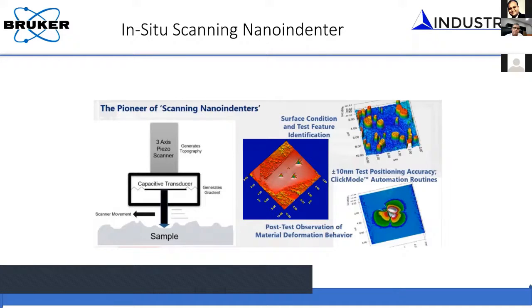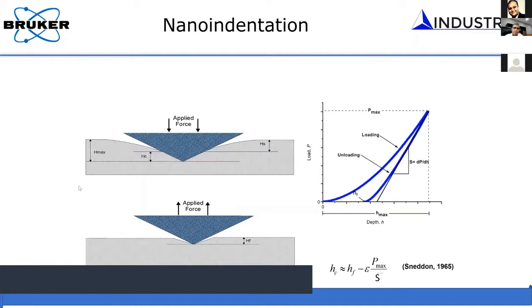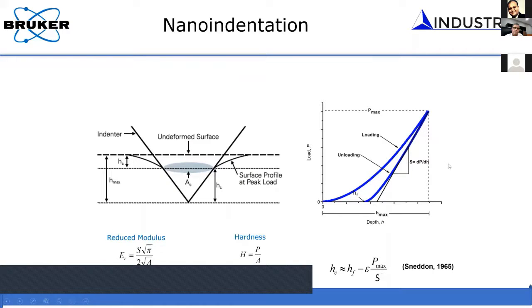And now I think I already covered that you can use this transducer to generate load displacement curves. And these load displacement curves are unique to the specimen material that we use. We call it a mechanical fingerprint. And from the unloading curve, you can measure the stiffness. And from knowing the stiffness and the area of the tip by calibration process, you can calculate the reduced modulus and hardness of the material.